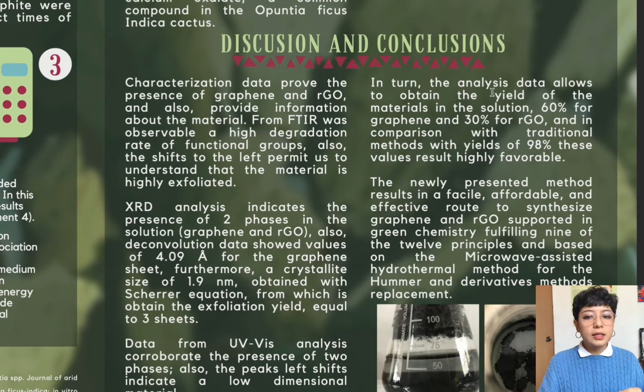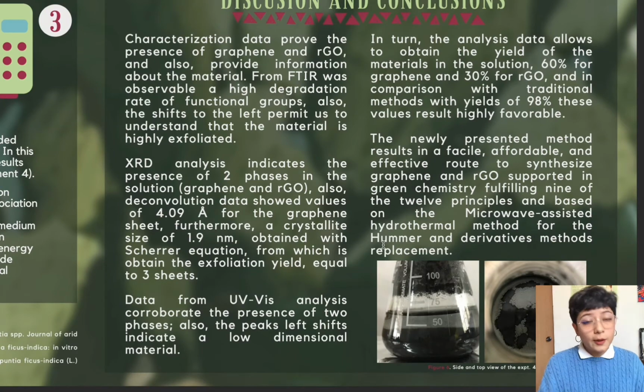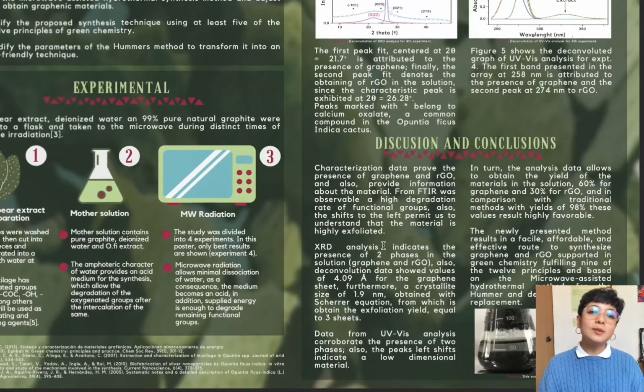In turn, the analysis data allows us to obtain the yield of the materials in the solution, 60% for graphene and 30% for RGO. And in comparison with traditional methods with yields of 98%, these values for a completely green synthesis route result highly favorable. The newly presented method results in a facile, affordable, effective, and overall scalable route to synthesize graphene and reduced graphene oxide, supported in green chemistry, fulfilling 9 of the 12 principles and based on the microwave-assisted hydrothermal method for the Hummers and derivatives method replacement.